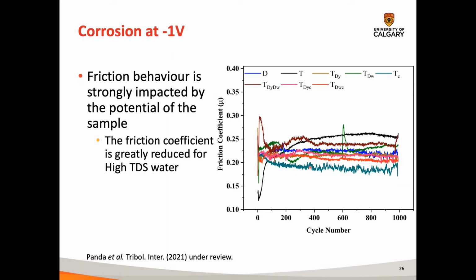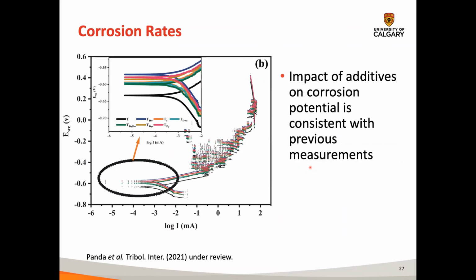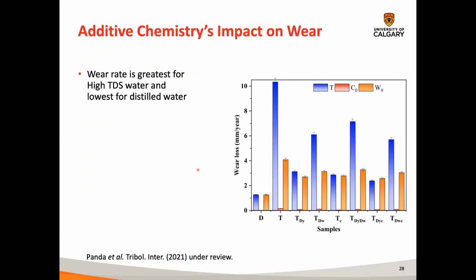the friction behavior. So we also did this polarization measurement, so we can see here the impact of the different additives on the corrosion potential, and then you can measure the Tafel slope from these curves here to figure out what the weight loss is per year, essentially just from corrosion. And then this graph here tells us essentially the total wear of the system. This is the wear due to corrosion, and this is the wear due to the mechanical sliding of the sample.